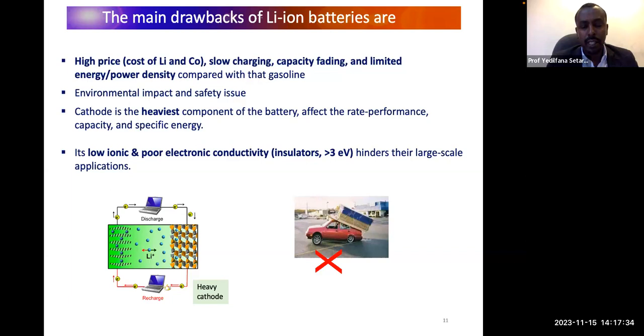The main reason behind the capacity fading, limited energy, which means specific energy capacity, and limited power density is mainly because of the cathode component of the battery, which is the heaviest component, and at the same time, an insulator. The cathodes, unfortunately, are supposed to be metals or good conductors, but the existing cathode materials, even the commercialized cathode materials, are insulators with a band gap of 3 electron volts. This actually hinders their large-scale applications.